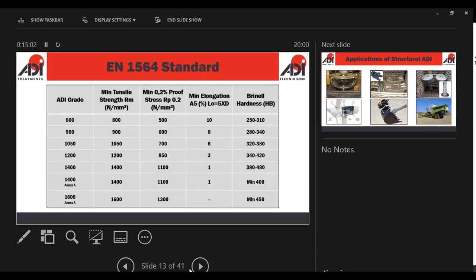As most of you know, we can achieve those grades of ADI by altering the heat treatment. The foundry manufactures a casting to the chemistry that we discuss with you, recommend and agree on. We austemper that, and just by changing our heat treatment, we can offer the ADI 800, 900, 1400. So once you've made that casting, we can alter the heat treatment to change the grade. It can be the case that a foundry makes a product, the customer tries it out on the vehicle or in the field on an agricultural wear machine part, and then decides that it's not wear resistant enough, or they need more ductility, and we can alter the grade. The foundry doesn't have to change anything. We just alter the heat treatment.